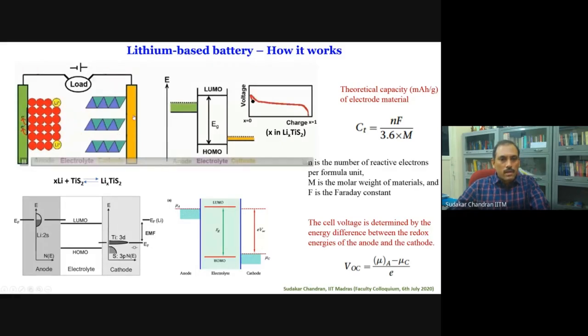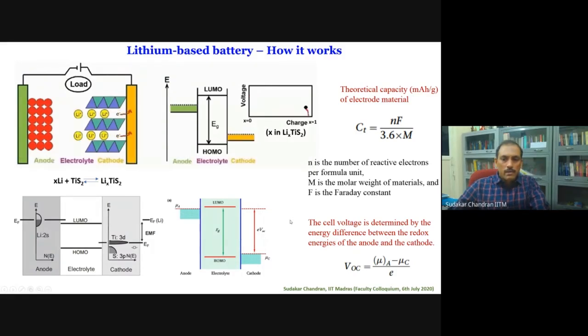You can also see that as the lithium goes to the anode, it gets filled up, the electrons get filled up, and then the Fermi energy moves, and the same thing happens on the other side as well. So the cell voltage is basically determined by the difference between the redox potential energies of the anode and cathode. For example, I have shown here clearly the redox potential of the anode and cathode. So this gives the net voltage.